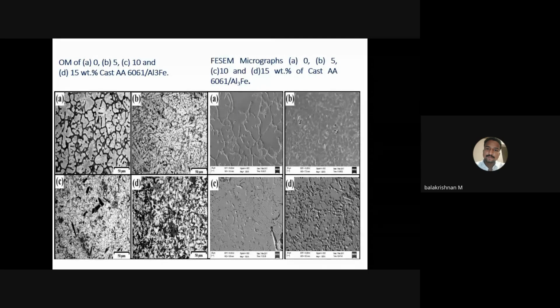So the particle manifests. In this case, most of the particles are in irregular shape, polygon, and square morphology. In other words, the aspect ratio of the particles decreases as the weight fraction is increased. Again, the nucleation rate increases as the weight fraction is increased. This increase in nucleation might restrict the growth of the crystal. So the intermetallic particles will restrict the growth of the nucleus while the casting settles down.